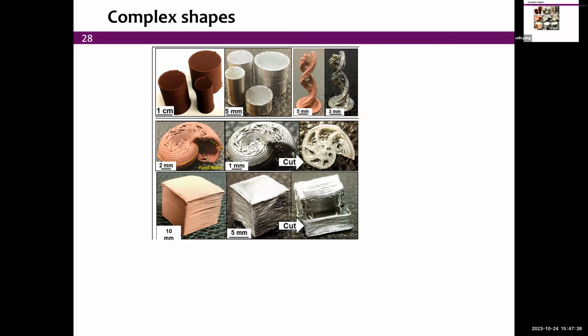We've seen the lattices. You can do structures that have open spaces. Here's a box, a fully enclosed box. We cut it. And so you see here, for instance, that the ink is sufficiently viscous that it doesn't sag as you're going from one end to the other. So we can really make closed structures, impossible with a powder bed, for which the powder would be entrapped in the closed cavity.